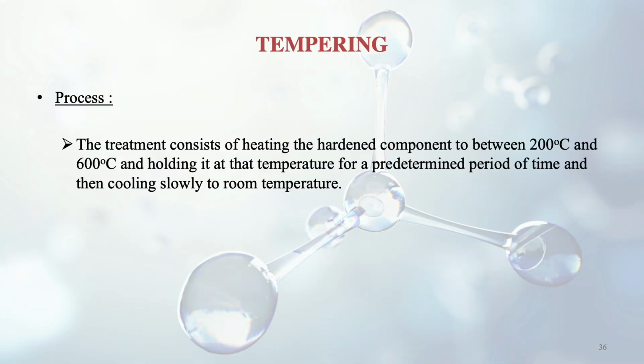In this treatment, heating of the hardened component is done between 200 and 600 degrees centigrade. So this is the range. We have to heat the specimen from 200 degrees to 600 degrees centigrade, and then hold it at that temperature for a predetermined period of time. So there are two main factors: one is the temperature range and the other is the time, for how long we hold it, and accordingly we will get different things depending upon the time we hold it at that temperature. And further, after holding it at that temperature, cooling is done slowly to room temperature. So this is the process of tempering.